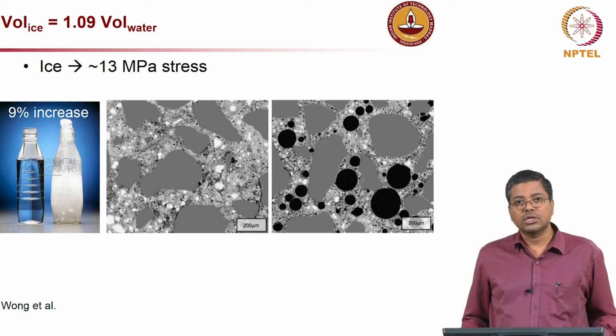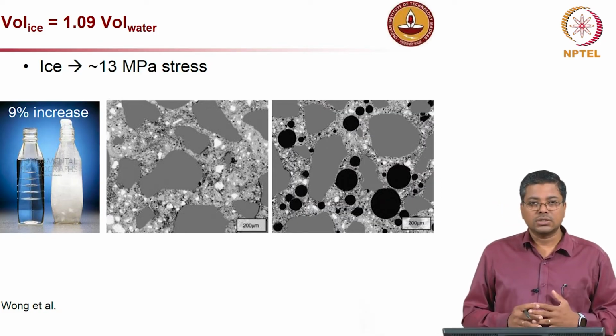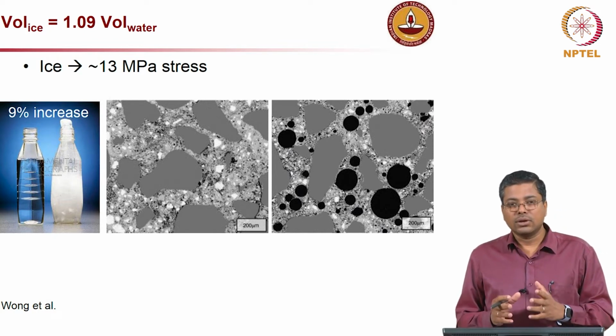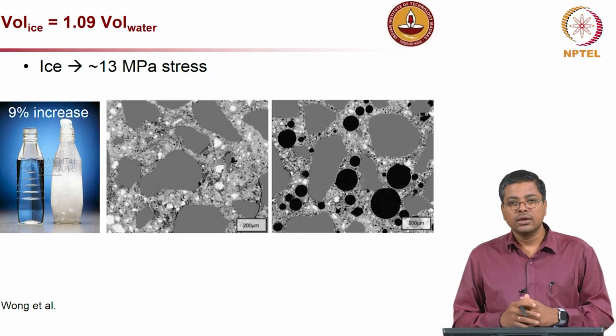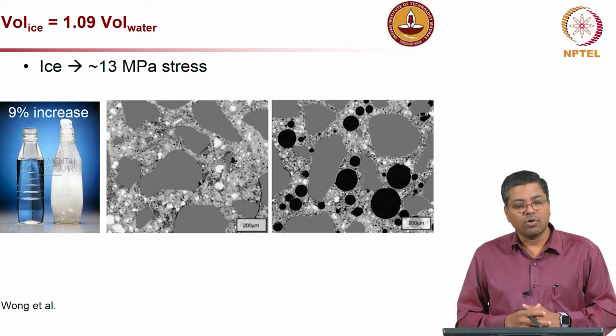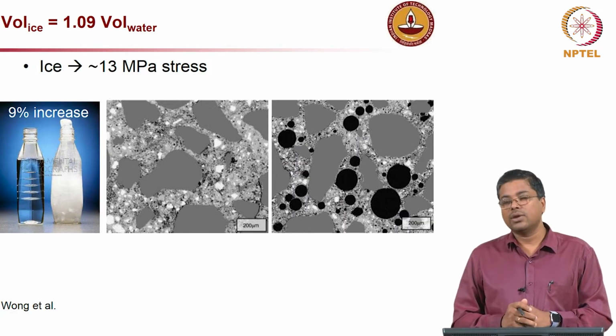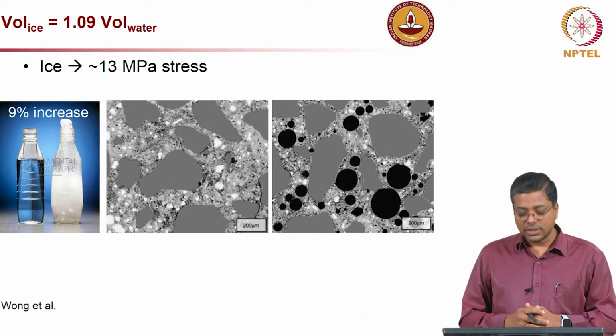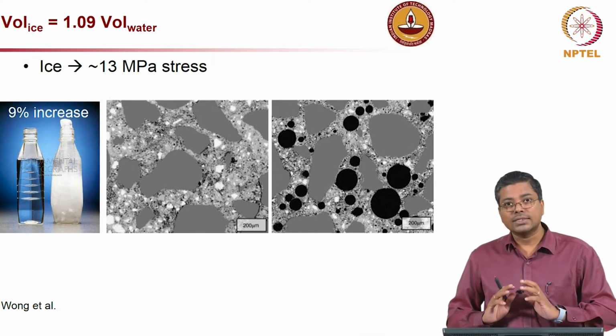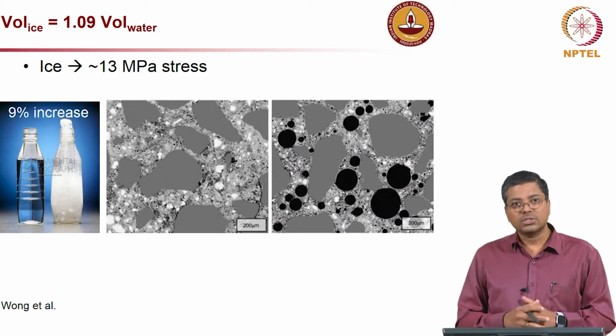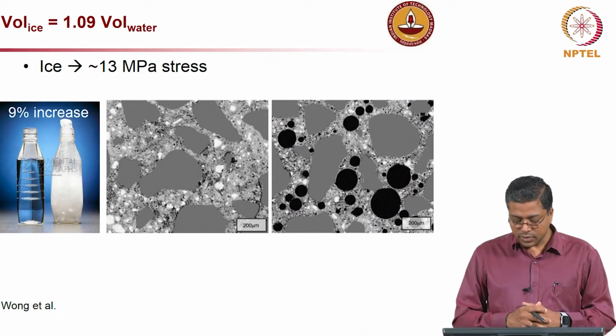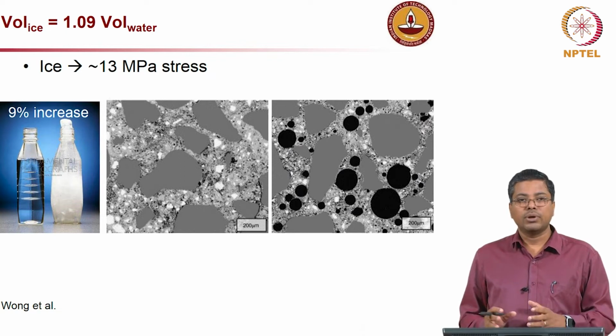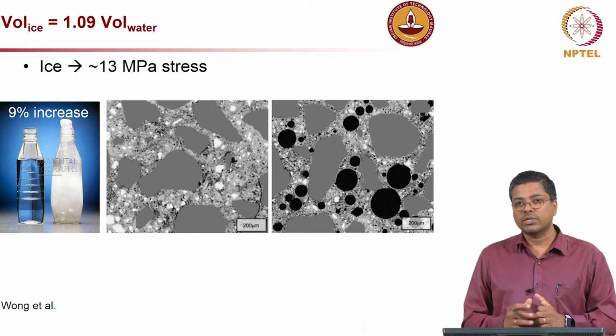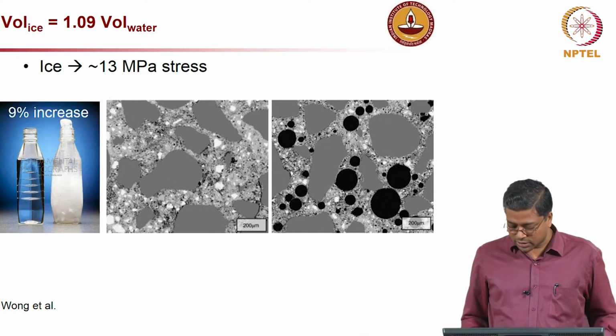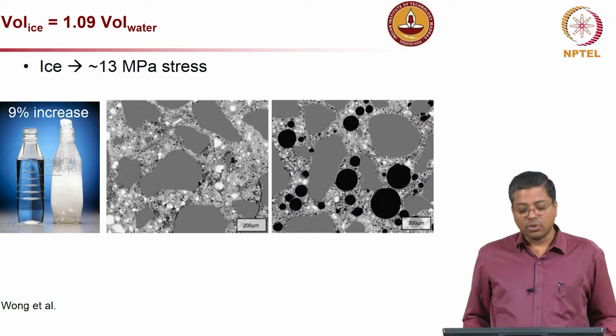The third picture shows how we can control this cracking. The black circles you see there are air voids which are introduced, entrained air voids, not entrapped, but entrained air voids. In other words, air is added as an ingredient in concrete, and we typically use about 5 to 6% of air by using chemical admixtures, air entraining admixtures. The idea is these air voids will provide space for ice formation without inducing any expansive stresses. This is the main idea of how to handle cold weather concreting.